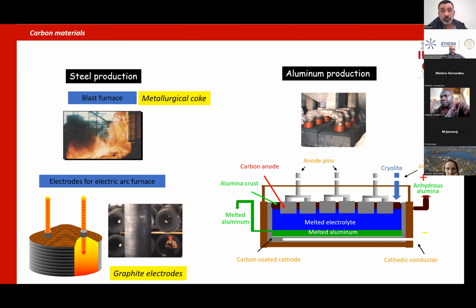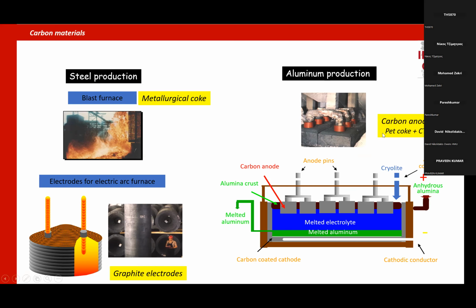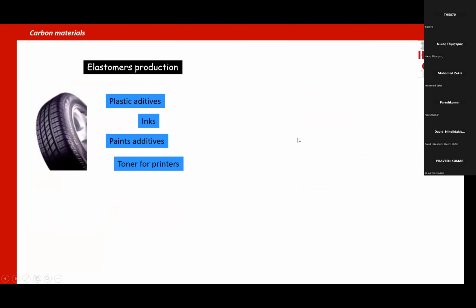All the aluminum produced in the world uses carbon in the production. Again, carbon electrodes that are consumed during the aluminum production. For every 3 kilograms of aluminum produced, you consume 1 kilogram of carbon. And in this case, this carbon electrode is made of petroleum coke and coal tar pitch.